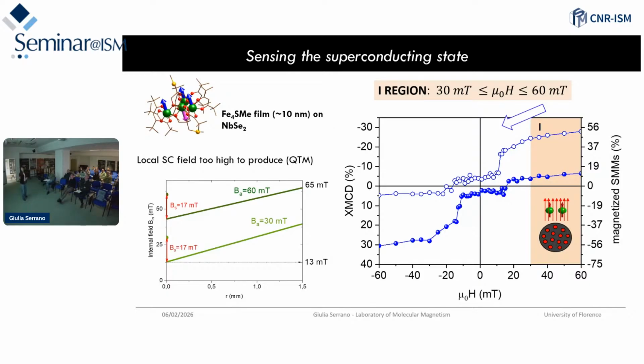But we know that there are vortices here, but the fact is that vortices are so dense that they produce just a very tiny oscillation with respect to the external field. So basically, the local field that the molecules explore is nearly the same as the applied field. So we don't see any strong deviation from the expected molecular behavior.